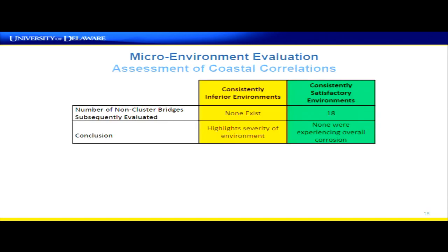And then a final way of looking at this, just for the coastal correlations, because we did have pretty good confidence that we looked at a good sample size here, we went back and found outliers in the NBI and then requested from the states their inspection reports. For that consistently inferior environment, there were no other bridges in the entire US that met that category that weren't a part of our study. So what that tells us is that that is a very severe environment that we identified.